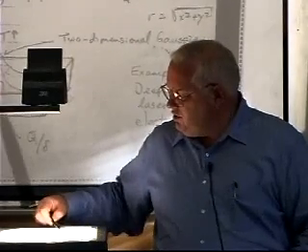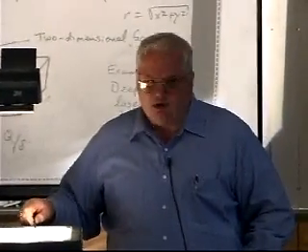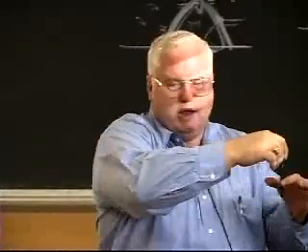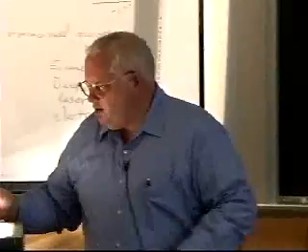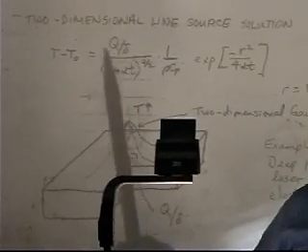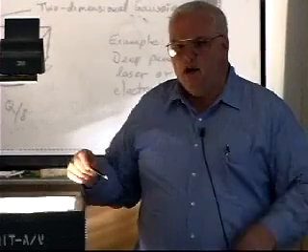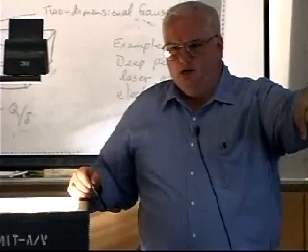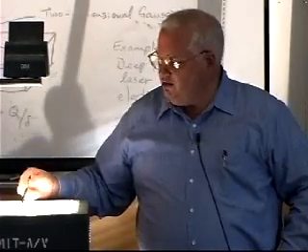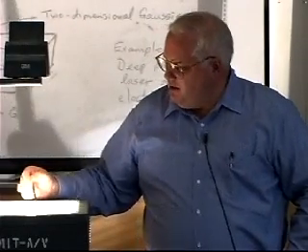For a two-dimensional heat source, I now have a line. So this one up here was friction welding, a planar heat source. A linear heat source is basically the same thing as a laser or electron beam, right? I drill this deep hole and move it along the plate. Well, in this case, I'm not going to move it. But you work that out, and it's the same old thing, only now instead of Q over A, it's Q over delta, where delta is the heat per unit length of that linear heat source. It's just a little line, as if I had a hot wire cut through butter or something. And now it's a two-dimensional Gaussian distribution. Same Gaussian, but now in terms of r squared, because I'm in axial coordinates, where r squared is basically just x squared plus y squared. There's the same rho c sub p.